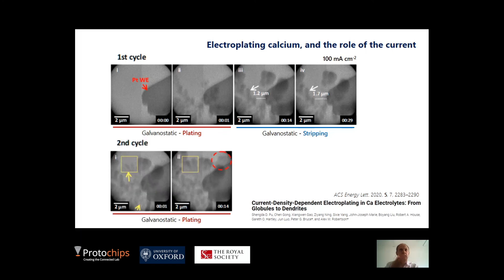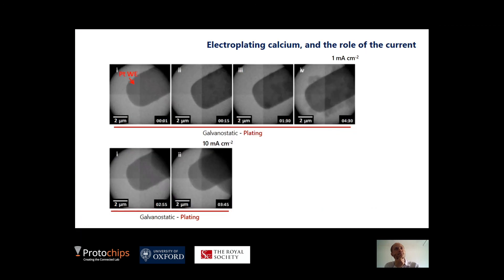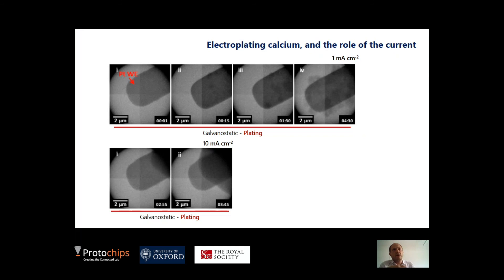In the subsequent cycle we can see further dendrites growing. What's quite interesting is we see the tip of this one, as shown in the yellow box there — instead of staying with this rarefied needle shape, it kind of turns into this chubby bump geometry. We talk a little bit about why that is in the paper. Looking at more realistic current densities — 1 and 10 milliamps per centimeter squared — we also see, most importantly, there's no dendrite formation, which is a relief. But at very low current density we instead see a very strong bias towards wanting to preferentially nucleate. Instead of these nucleated calcium sites growing, we get lots of small nucleation sites — a strong preference towards nucleation. Then as we increase the current density further, the rate of calcium plating increases, and instead of nucleation we seem to see uniform growth of a few globules — just one large deposit continually growing rather than lots of nucleation events. This helps us understand some of the trade-offs between deposition rate and the rate of formation of a passivation layer.